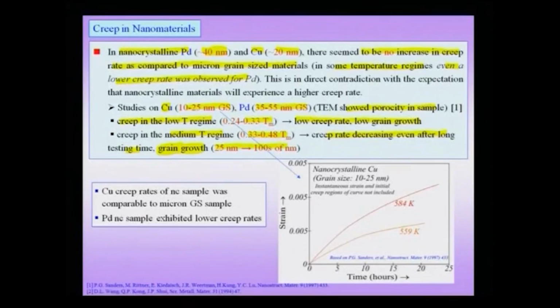And here we are not talking about a small grain growth, we are talking about a grain growth wherein the grain size increased by a factor of 4 or more, and this we are talking about the average grain size, which implies that the microstructure is continuously changing. Maybe there is also porosity in the sample which is increasing, and therefore, it is difficult to characterize creep in many of the nanocrystalline materials, because I cannot understand if this decreased creep rate is occurring because of the nanocrystalline effect, or is it occurring because of the increase in grain size which is taking place during the testing.